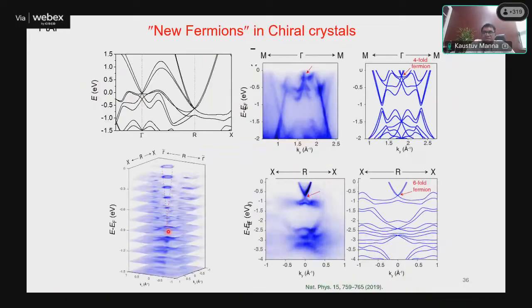So this is our experimental verification. We have done the ARPES measurements, and at the gamma point, as you can see, this is the four-fold degenerate band crossing. At the R point, we have the six-fold degenerate band crossing.